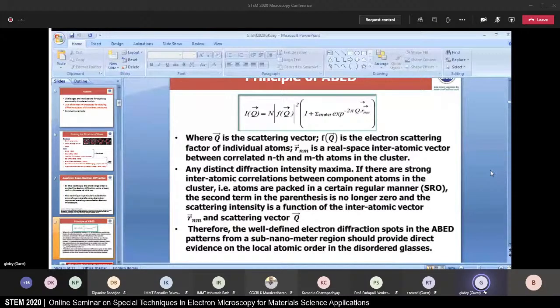The equation here shows the intensity of the diffracted beam from a small cluster where you have two atoms, one located at position N and the other located at position M. There is a vector joining them, and you also have the scattering vector Q, and FQ is the electron scattering factor. So you can have a diffracted beam from a regular structure, even with two atoms, but not in a gas. In gas also you have atoms, but they do not diffract the same way as in a solid, even though the solid is not crystalline.